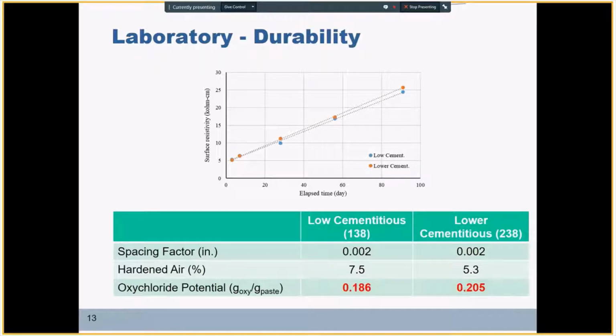Also, the hardened properties of these mixtures were investigated. The air void system of the concrete mixtures was investigated in hardened state. We had very good spacing factor data, 0.002 inch for both mixtures, and over 5% air in hardened state for the two mixtures, again pointing to a good air void system and hopefully good frost durability in the future.